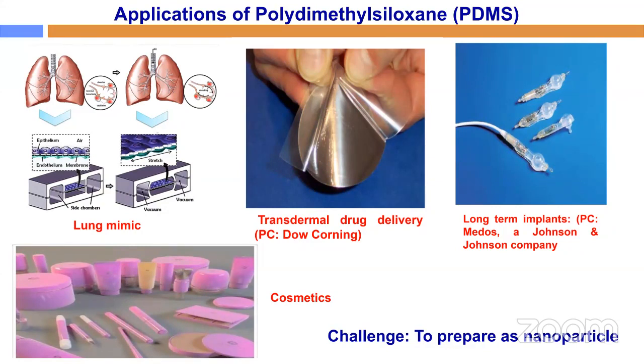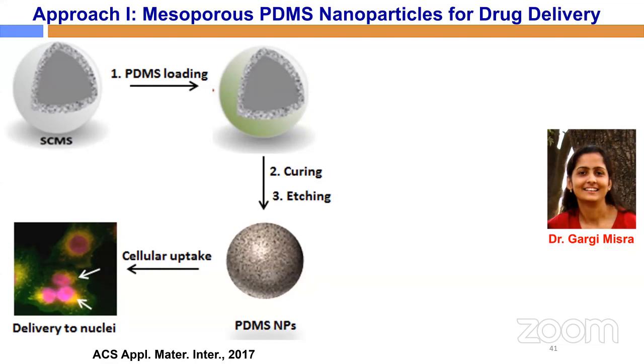But the challenge is preparing it as a nanoparticle, because PDMS polymer tends to form a film and will not form a nanoparticle, because of its surface energy. So what technique should we use? Gargi came up with a nice idea: if we confine this polymer into the pores of a material and then do the cross-linking, the PDMS will not form a film. So, as earlier, she made solid core mesoporous silica particles and loaded the PDMS. She did the curing and cross-linking, and then removed the silica. She got nice, monodispersed, very soft PDMS nanoparticles of 200 to 250 nanometers.